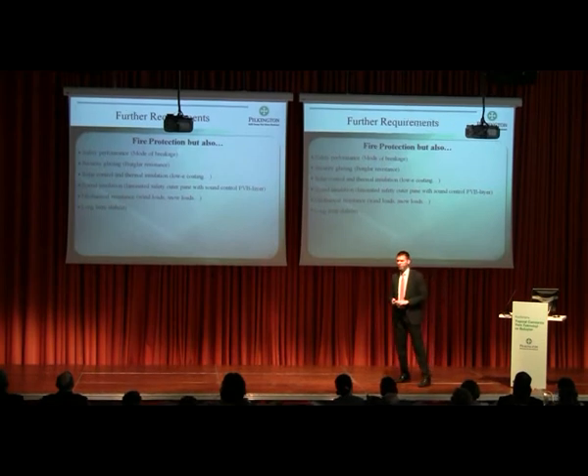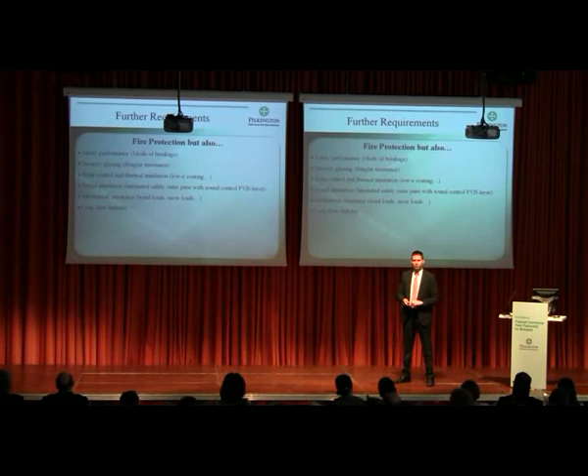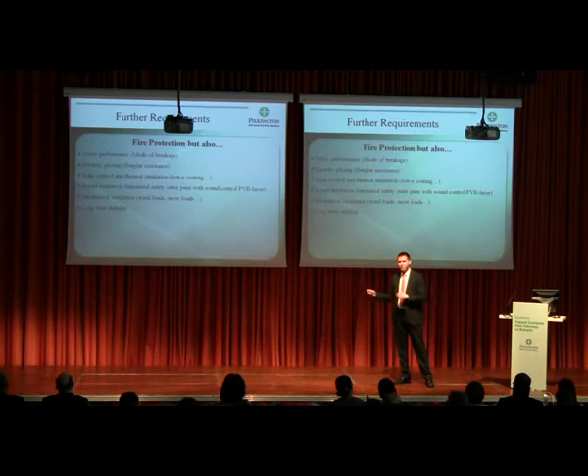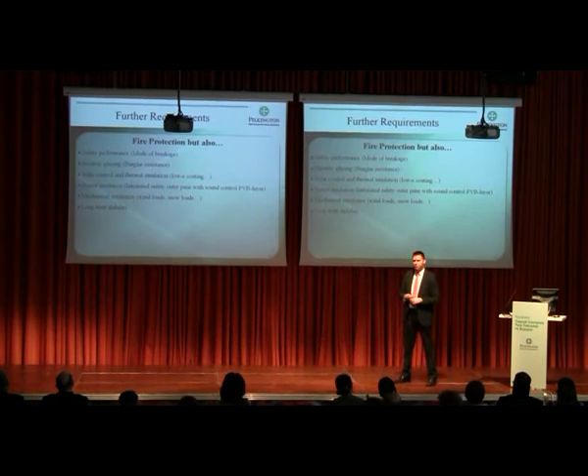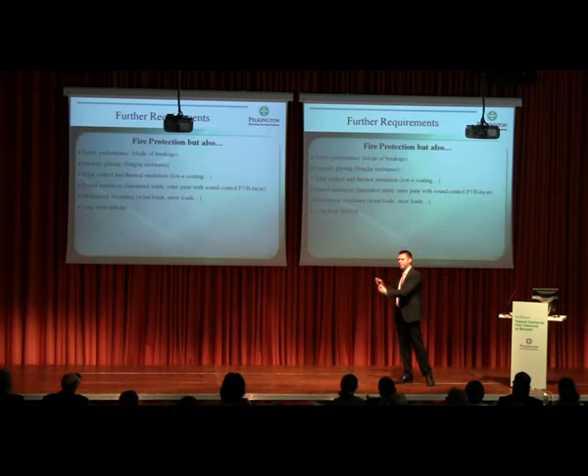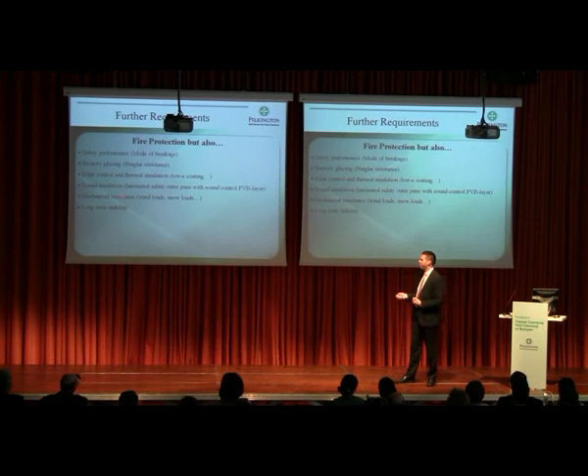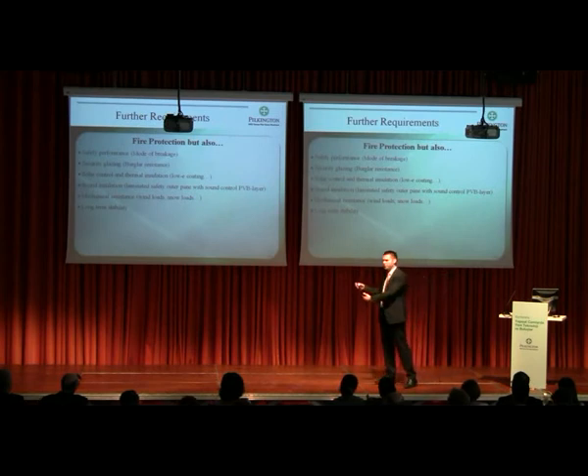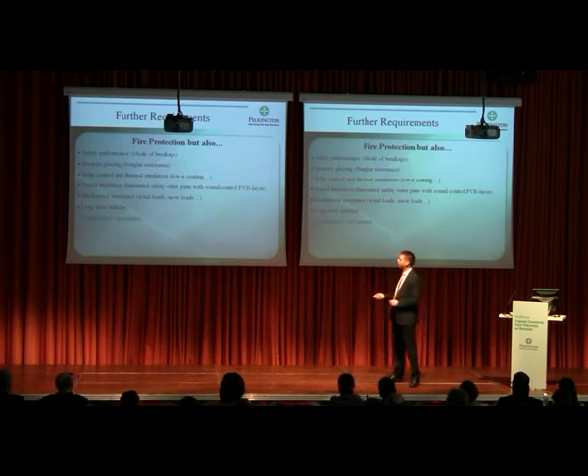Long-term stability. I told you that we started with a business more than 30 years ago, so we had the chance to take some panes from a building which were installed for more than 20 years, and we took those panes due to renovation of the building. We took those panes out and tested them internally and officially, and it was proved that the behavior after 20 years was still the same as we would have produced it today. So the performance of glass installed for more than 20 years is still perfectly given.